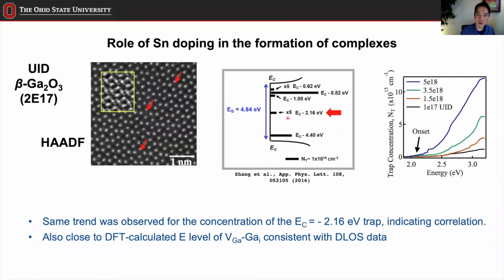Okay. So this particular one has the energy of EC minus about 2 eV. So that's about 2 electron volts apart from the conduction band here. And then one other thing that we can correlate is what DFT says about the defect energy. So when the interstitial-divacancy complex forms, the theory suggests that the value of the trap state energy would be somewhere around here. The calculation does not actually give the exact number, but the ballpark figure is somewhere around there, which includes the number that's also measured. So, okay, that's also something we can correlate. So there's a three-way correlation between what's predicted by the theory, what is measured by the optical spectroscopy, and the direct observation by microscopy. Okay, so that's what we were able to do here.